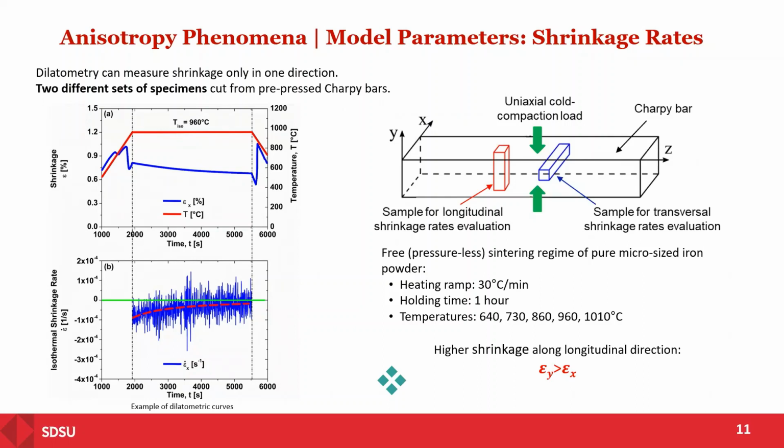And that's why it makes sense that when you have an isostatic state of stress, when you apply the pressure from all sides, you don't get anisotropy. So my point is the anisotropy is based on how you compact it, the geometry, not really... The anisotropy is driven by the technology. Yeah, it's because we only actually compact these parts.